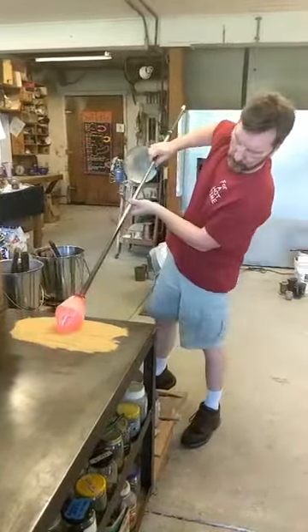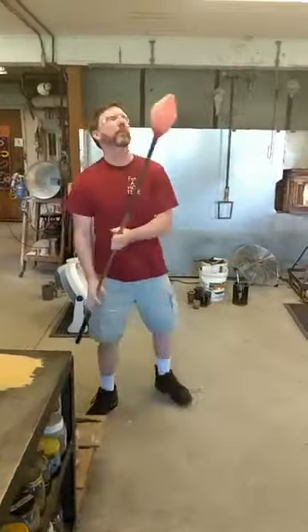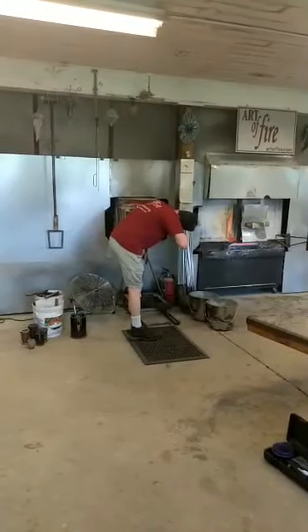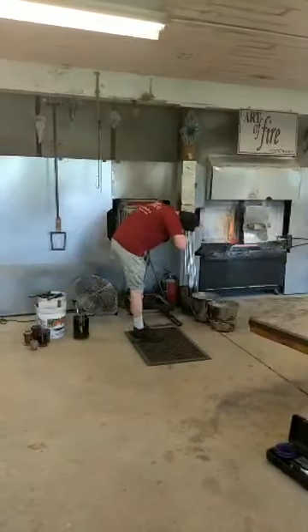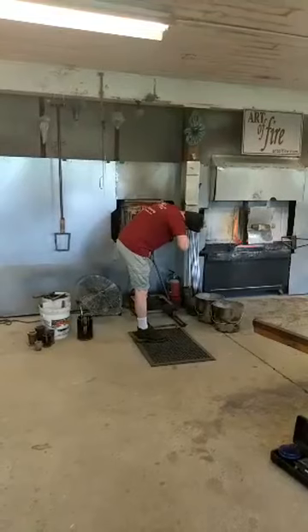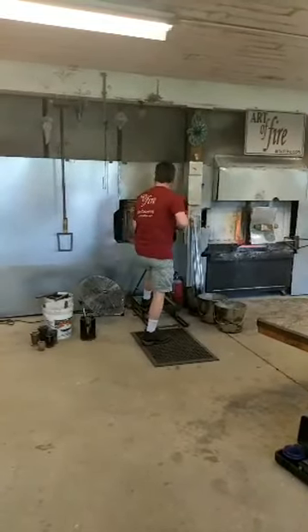How long does it take for the glass to melt and come to the right temperature? Well, Barbara, if you're talking about the glass in the furnace, it takes about an hour and a half to get it from our regular operating temperature up to a melting temperature. Then we load the furnace with the glass batch, we call it. It's the powdered glass. And we do that in several stages, because rather than load it with 150 pounds of raw material and cause the furnace to work so hard to melt that, we go in with smaller amounts till we get to whatever we need, perhaps 150 or 125 pounds, whatever the case may be. Great. Yep, in the furnace, Barbara says. So I am answering the right question.